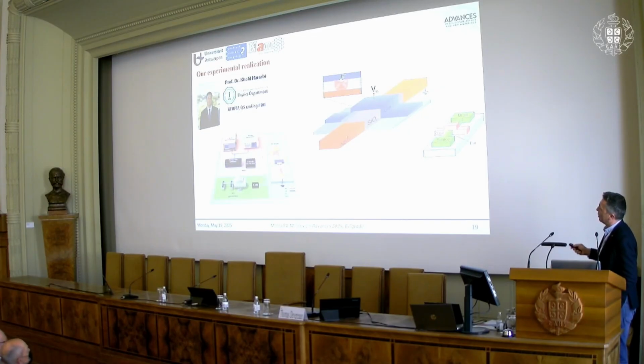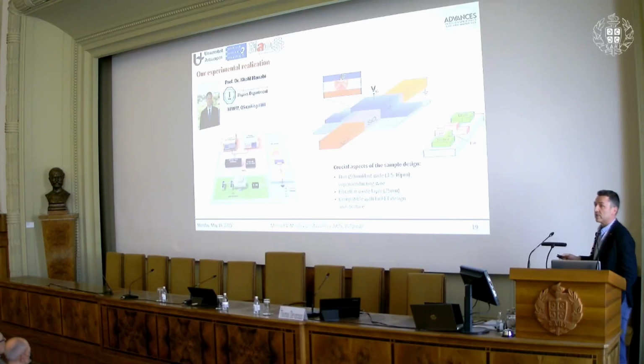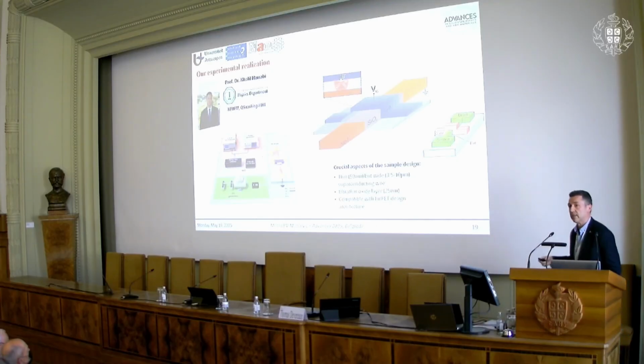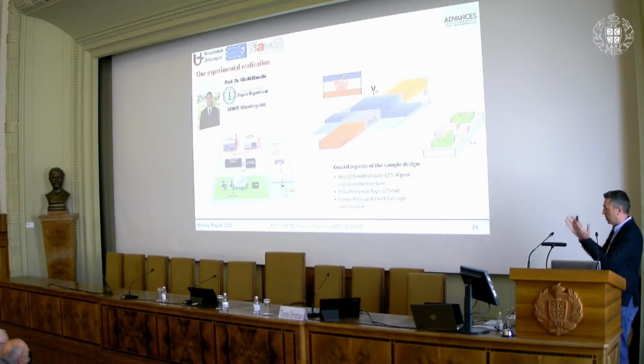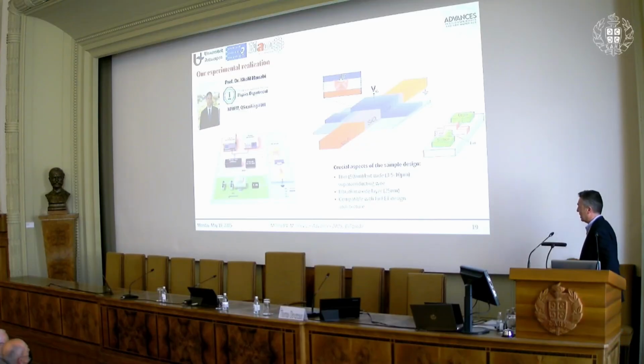This is the system that we designed: a niobium titanium superconducting stripe of width 3, 5, or 10 microns, so significantly larger than the previous one. Thin, 50 nanometers thin, so that we have uniform gating across. An ultra-thin oxide layer, 25 nanometers, and then the gate coming all around. This is the so-called FinFET design architecture, so we are sure that we have gating from all sides of the stripe.